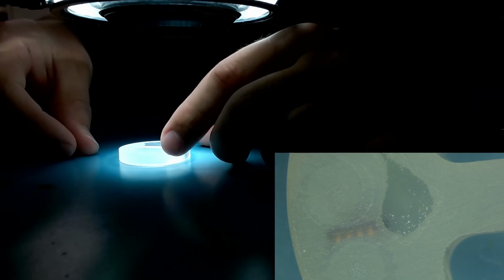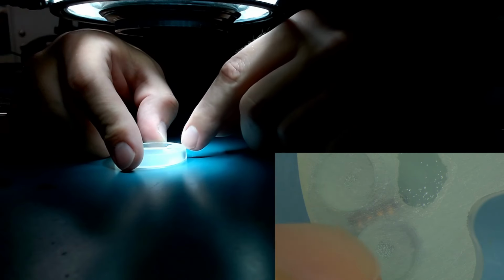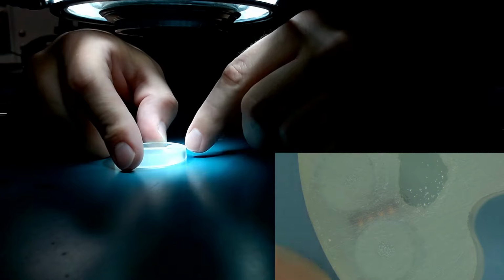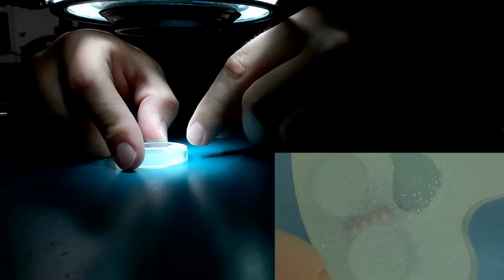And now it's been a couple minutes of polishing. The sample has been removed and rinsed, and we're looking at the back side still. The surface is pretty uniform. There's one little spot here where there's a small depression, but it's not enough to worry about polishing any further. The important bit is that right behind the device, we do have a flat surface we can use as a measurement datum. And now flipping over to the front, we're going to take a thickness measurement of the whole sample.